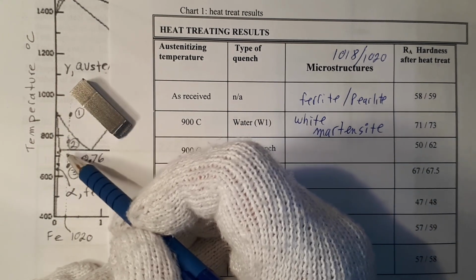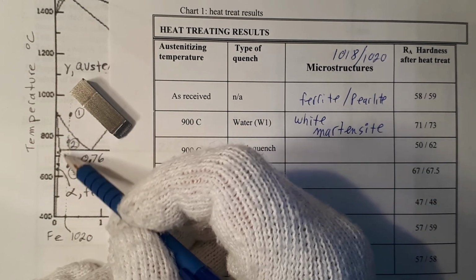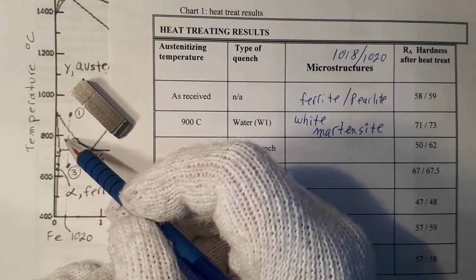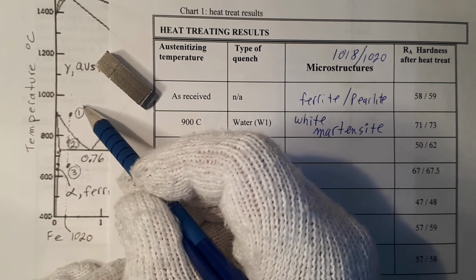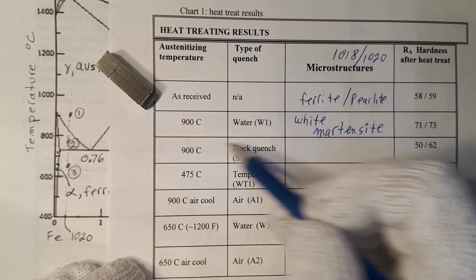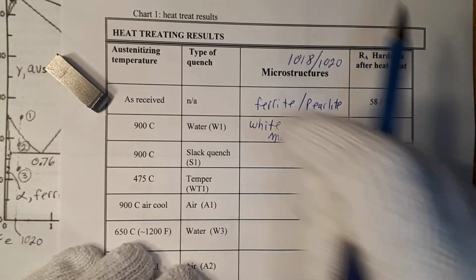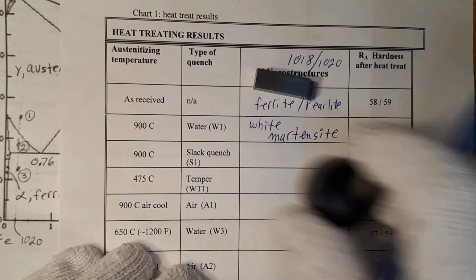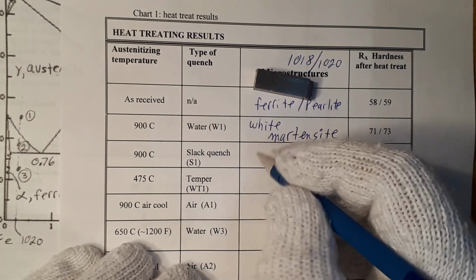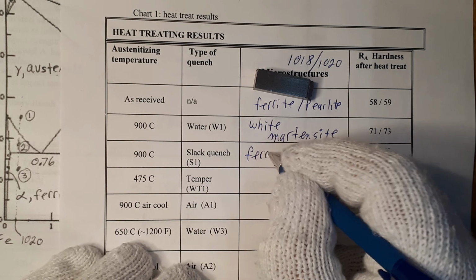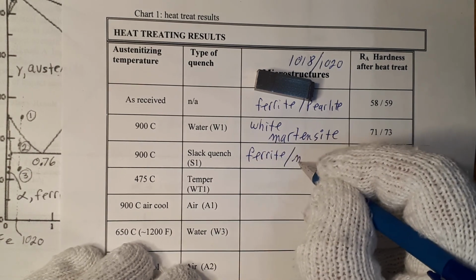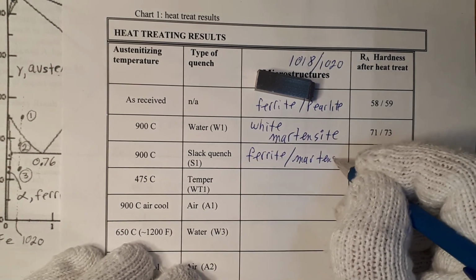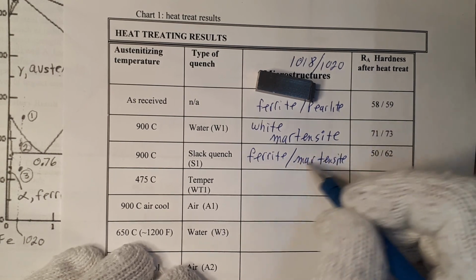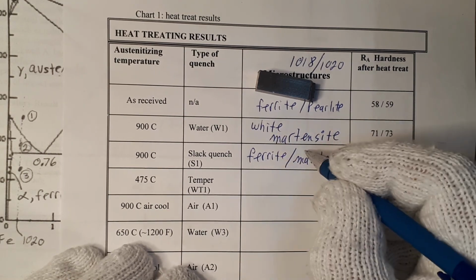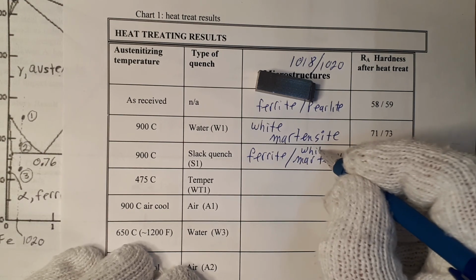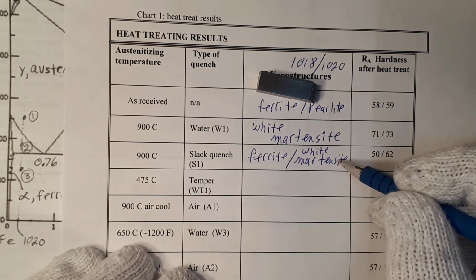The ferrite will remain ferrite because it won't transform, but the austenite is unstable at room temperature, and the austenite will do exactly what this austenite did. It will form martensite. So the microstructure, when we look at this in the microscope, will be a combination of ferrite and martensite. Again, this particular martensite has that special name of white martensite to indicate there was no tempering done. It was as quenched martensite.